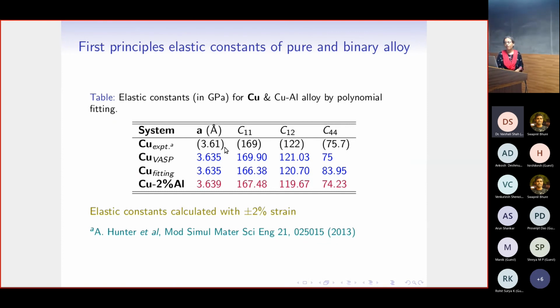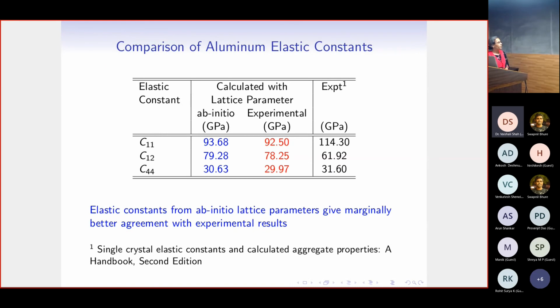So we see that, and these are the actual experimental ones we expect. So we see that whatever we obtain by the fitting is actually quite well in agreement not only with the VASP inbuilt module, but also in good agreement with what is experimentally reported. Which means that we can follow this methodology for all other systems that we are interested in. We did this calculation for a set of percentage dopants for aluminum and copper, but I'm just showing you data for one case. So we follow this methodology and we obtain the elastic constants for aluminum.